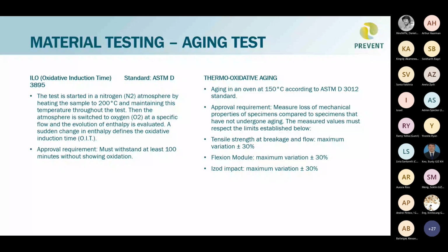The other one is thermo-oxidative aging. So the plastic is put in an oven at 150 degrees C. And then you measure the loss of mechanical properties of the specimen compared to a specimen that didn't go through this process. So you compare a sample not tested with the one tested. And the difference in tensile strength at breakage and flow: maximum variation of 30%. So all those factors should not vary by more than 30%.